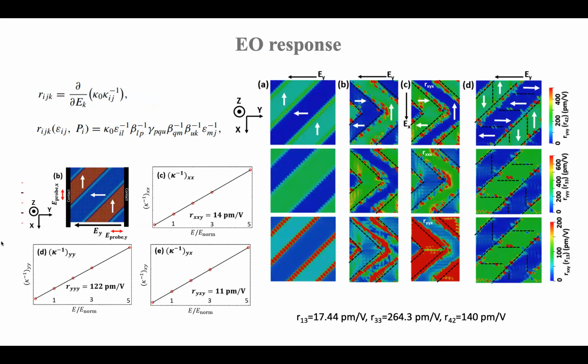And so you can do it two ways. Because I have the full expression, I can actually take a derivative of the dielectric tensor and analytically calculate what the Pockels coefficient at every node is. And this is what I'm showing here. But I also can just apply the field and measure it, so to speak, computationally. I look at the various components of the dielectric tensor at various values of the field, which is normalized to some fixed value. And I take the slope, and that is the Pockels component of the tensor.